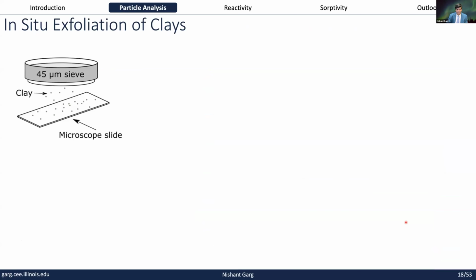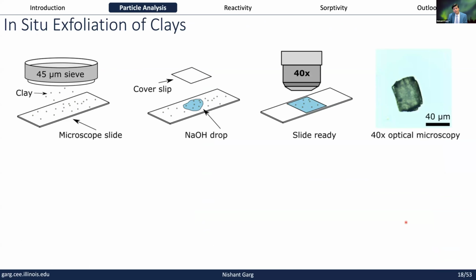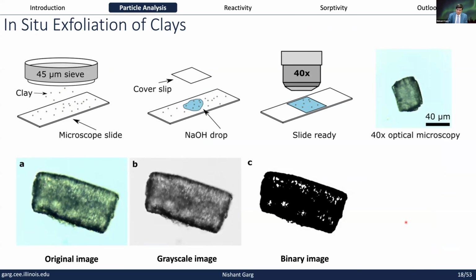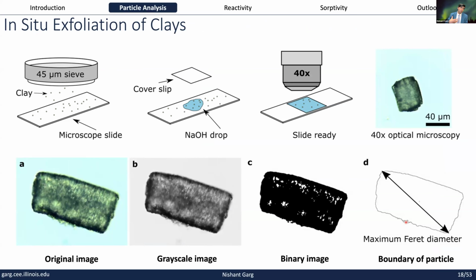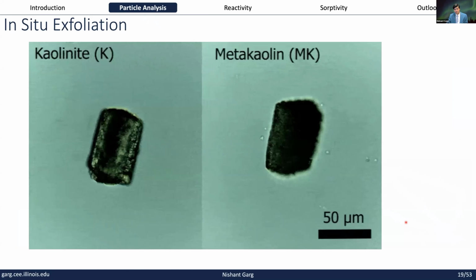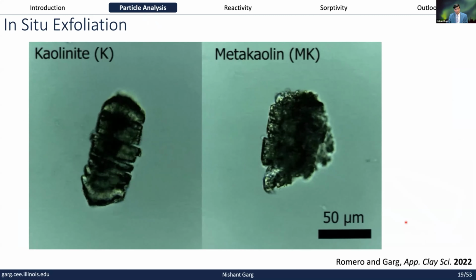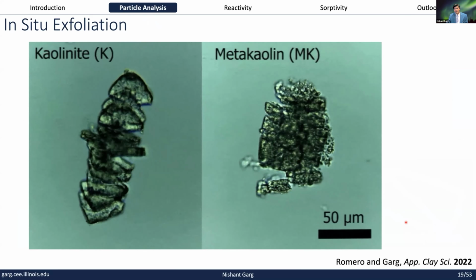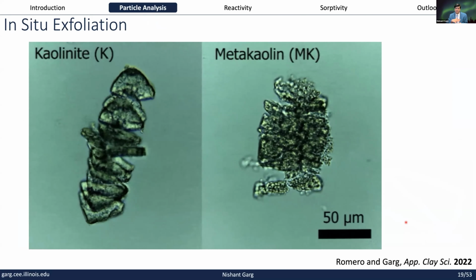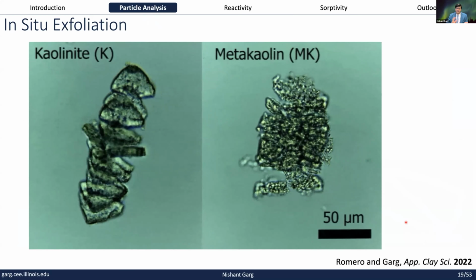We've also been looking at single particles of clays, because one of the issues with clays, and calcined clays in general, is that their water demand is quite high, and we have to really understand what's happening here. So one of my students, Pablo, did this very interesting experiment where he isolated single clay particles under two glass slides, and we were able to figure out what's happening. It turns out, if you look here, kaolinite opens up nicely. This exfoliates like these individual potato chips, and this is well known.